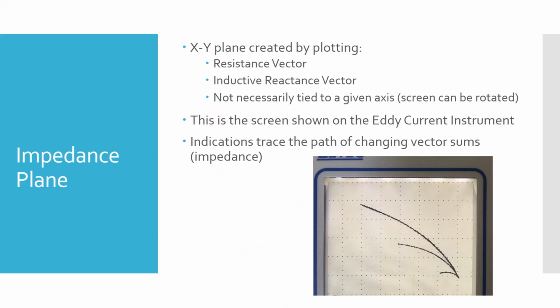And if we start to slide our probe across the surface of the part, as long as nothing changes about the part, as long as the thickness doesn't change, as long as we don't go across a crack or a flaw, as long as the geometry doesn't change, that impedance and inductive reactance aren't going to change. And so that point will stay at its origin down here, wherever we set it. We can set it where we want, but typically with cracks, we put it in the lower right corner.